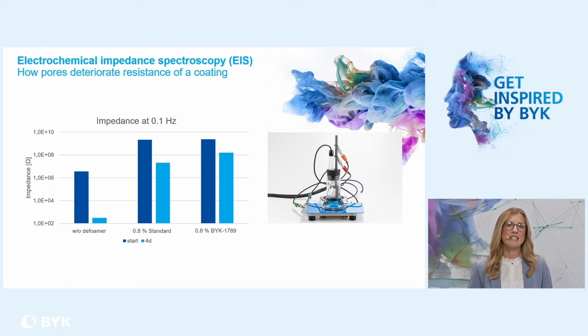BYK-1789 is the first defoamer which has been especially developed for water-based and airless spray-applied high-build systems. And by using this newly developed defoamer, the electrical resistance of the coating is improved in a significant way. And therefore, BYK-1789 provides a considerable contribution to a long-lasting protection layer and therefore to a sustainable coating.